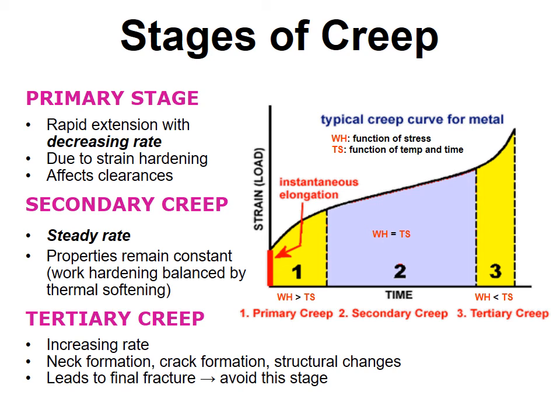Into the final stage of creep, also referred to as tertiary creep. It will commence when damage to the microstructure of the metal takes place. Here, the strain rate accelerates as the microstructure deteriorates with the formation of cracks, necking, and structural changes. After enough microstructural voids have been created, the metal eventually fractures and fails completely.